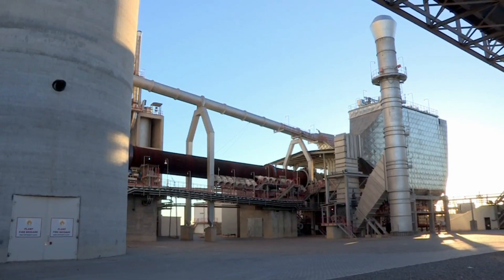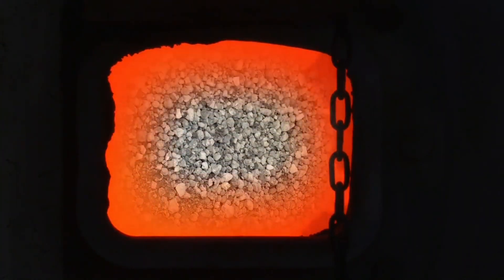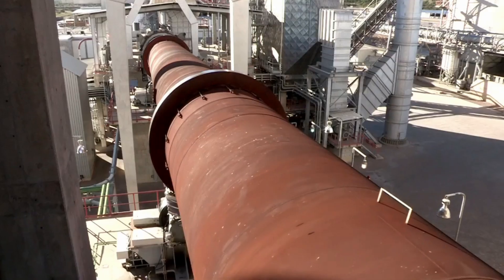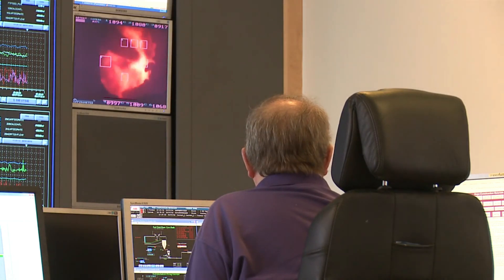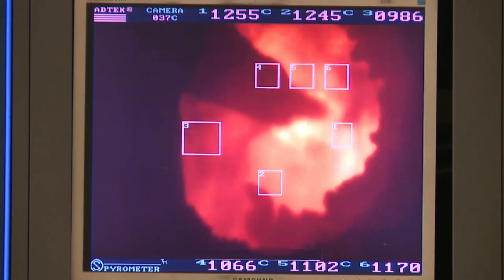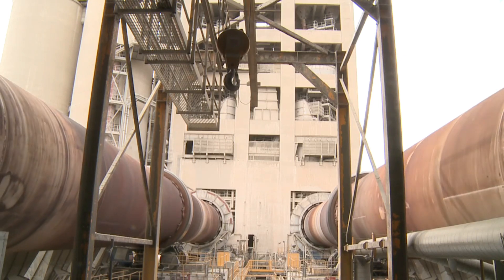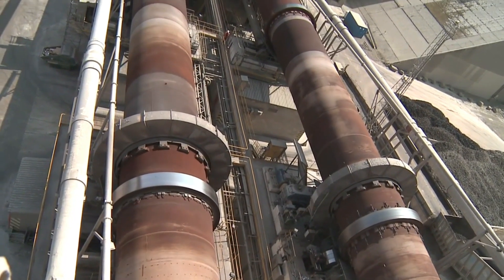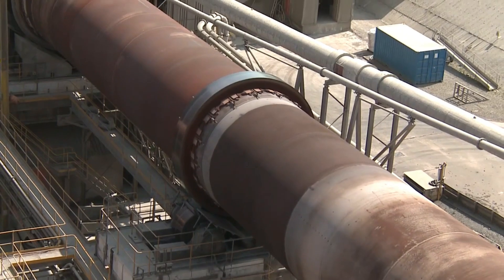The raw meal must now be preheated at about 900 degrees Celsius with hot gases from a kiln. This preheating process burns off any impurities in the raw meal and prepares it for the next stage, called pyro processing. Pyro processing is one of the hottest industrial processes and requires a tremendous amount of energy, traditionally in the form of fossil fuels. It involves placing the raw meal in a large rotary kiln at temperatures ranging from 1,350 to 1,500 degrees Celsius. These kilns are up to 200 meters long and 6 meters in diameter in wet process plants, but shorter in dry process plants, and are made of a steel cylindrical shell lined with refractory materials.